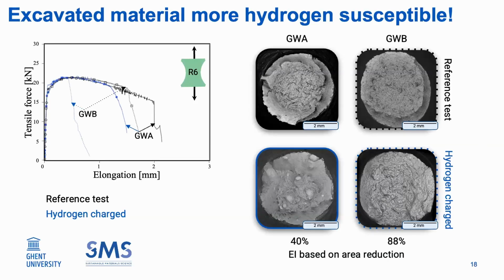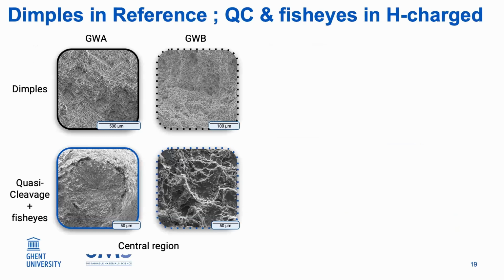Similar behavior is also seen for the welds, in that GWB had a higher degradation than GWA. In the fracture surfaces, apart from the brittle fracture like quasi-cleavage, we also saw fish eyes in these welds. A quantitative figure is that GWB was 88% embrittled in contrast to only, okay, not only, but 40% embrittlement. And this is based on the area reduction.